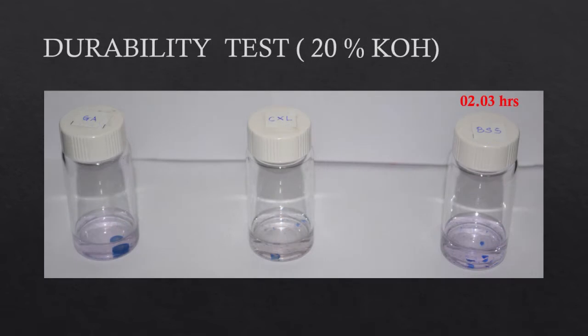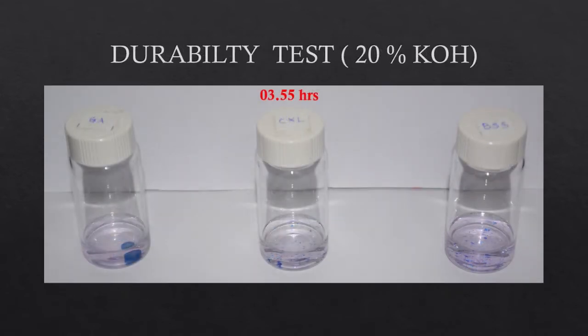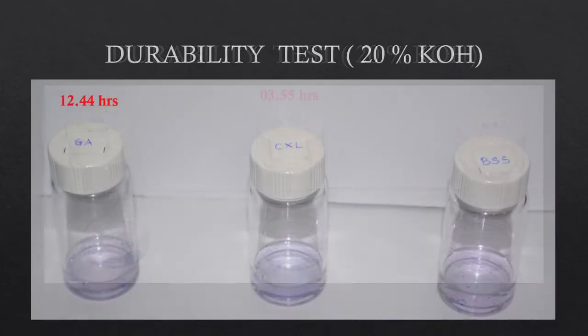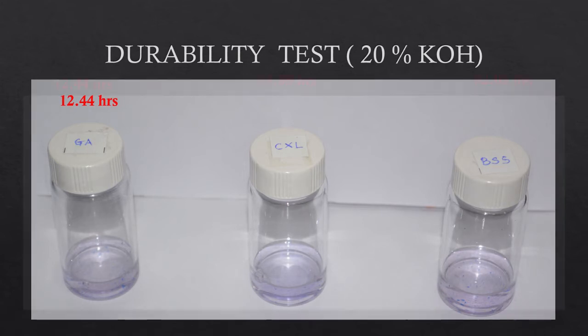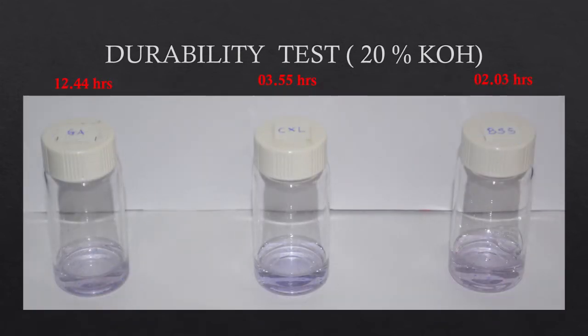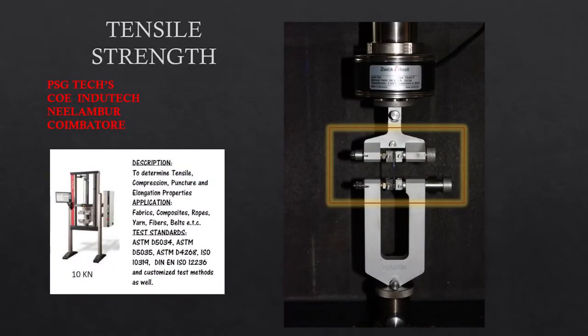The tissue treated with BSS dissolved at around 2 hours and 3 minutes, followed by the cross-link treated tissue which dissolved at around 3 hours and 55 minutes. The tissue treated with glutaraldehyde resisted disintegration till 12 hours and 44 minutes, thus proving that the glutaraldehyde treated tissue was the most durable one. As all these tests were only qualitative, we did the tensile strength test to quantify the strength.